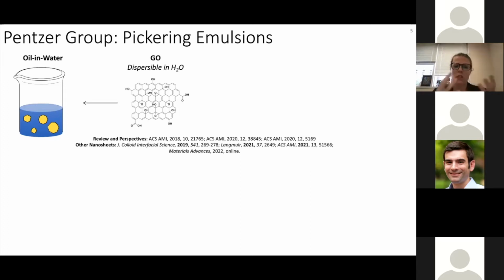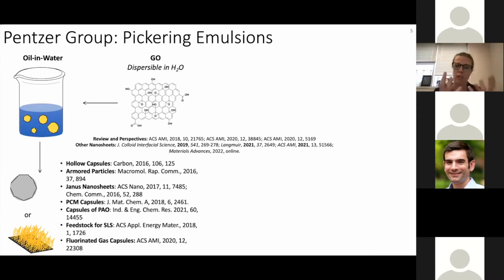We used this just as a platform for controlling where the reagents are, and did things like chemically cross-linking the nanosheets when they're at the interface to make capsules that we could then remove the oil from on the inside. If we use an oil that's polymerizable, such as styrene, we can make a solid polymer particle armored with the GO nanosheets. And then we could also use this interfacial assembly of the nanosheets to selectively modify one face of the nanosheet with an initiator for ATRP, and then do a grafting-from polymerization, so make these Janus type nanosheets.